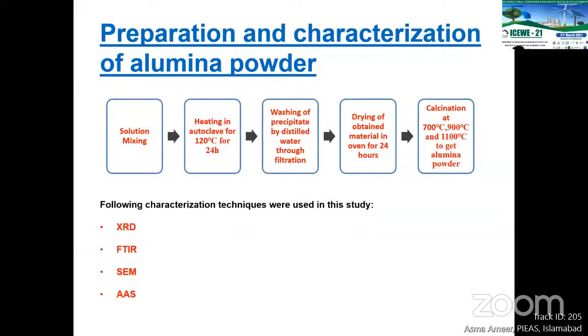Next was the drying, and it was dried in an oven for 24 hours at 85 degrees C. After drying, we got powder, which was AACH, ammonium aluminum carbonate hydroxide, which is the precursor for alumina. Next was the calcination of this AACH powder. In my study, AACH was calcined at 3 different temperatures, that is 700 degrees C, 900 degrees C, and 1100 degrees C to get the alumina powder.